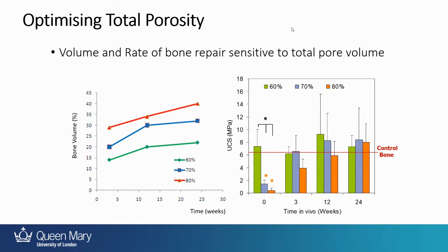Okay, and one of the other things we looked at is, again, what happens if you change the total porosity? So if you imagine something being 80% porous, I think the materials I pass around are probably around 80% porous. When we were first starting to work in this area, people wanted things that were a lot less porous because they thought that they needed to be strong. So, you know, lots of materials being produced with sort of 60 and 70% porosity, and not so much around 80% porosity.